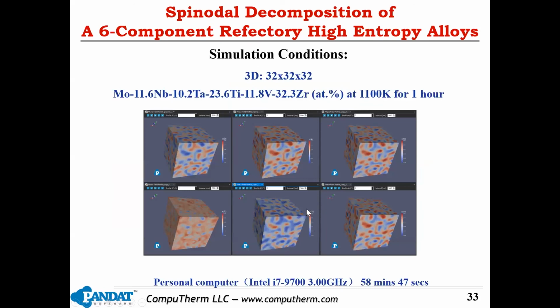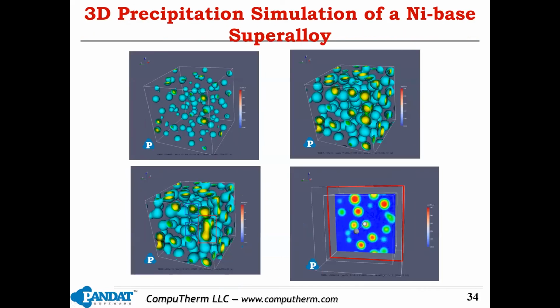Here, I just want to show you a few examples. This one is a simulation for a 6-component refractory high entropy alloy, and it's a spinodal decomposition. For this 6-component alloy system, it takes less than an hour using your PC. So it's very manageable, okay? The second example is a 3D precipitation simulation of a nickel-based superalloy. As you can see, the nucleation and the growth for this alloy can be clearly viewed from the 3D microstructure evolution figures, okay? And if you want to see a 2D view in a certain section, you can certainly do that, okay?